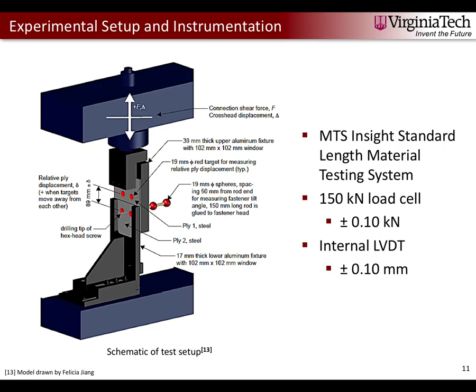Here's our experimental setup. We're using the MTS Insight standard-length material testing system located in the creep room at the lab. The system has a 150 kilonewton load cell measuring applied force at an accuracy of 0.1 kilonewtons. There's also an internal LVDT measuring crosshead displacement with an accuracy of ±0.1 millimeters. What's unique about our test setup is two aluminum window fixtures that allow observation of the specimen and provide lateral restraints so the plies don't separate or move out of plane.